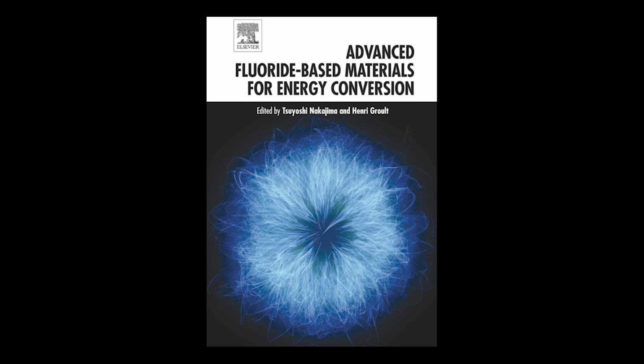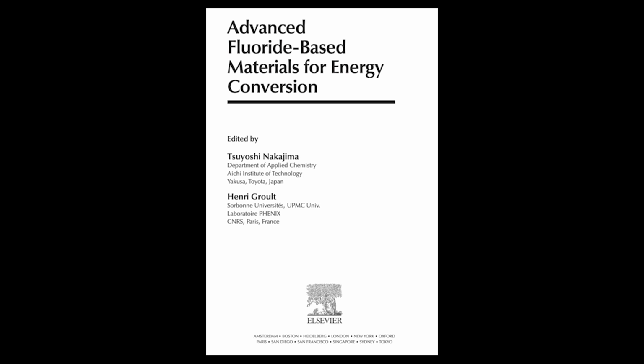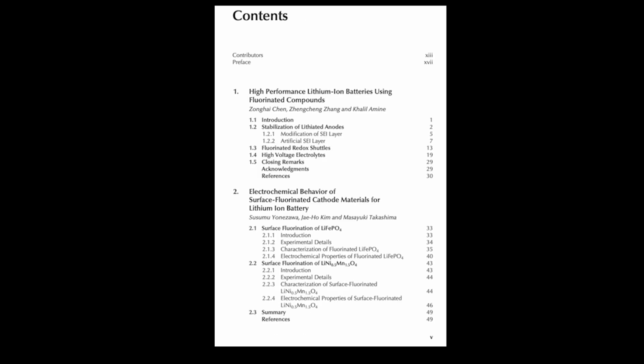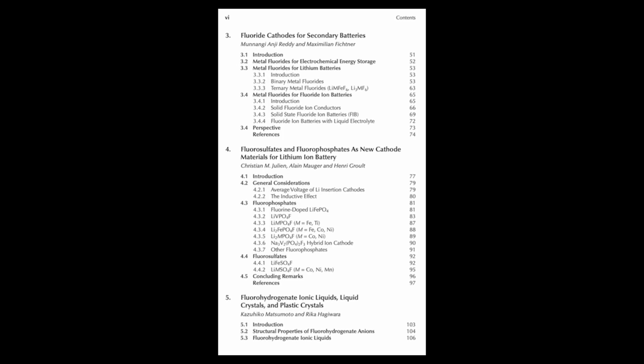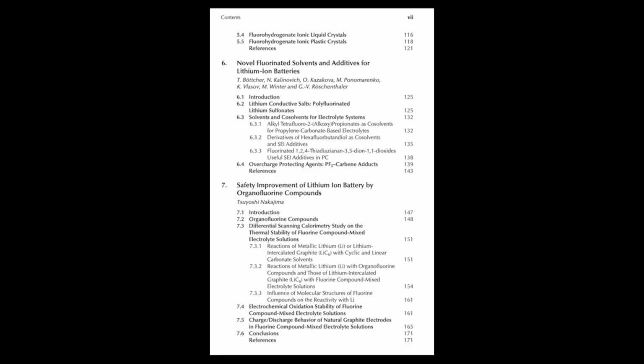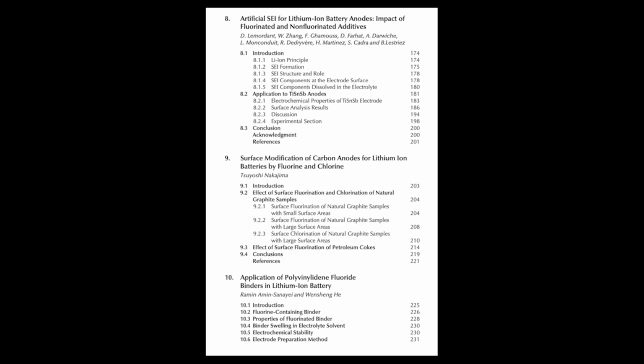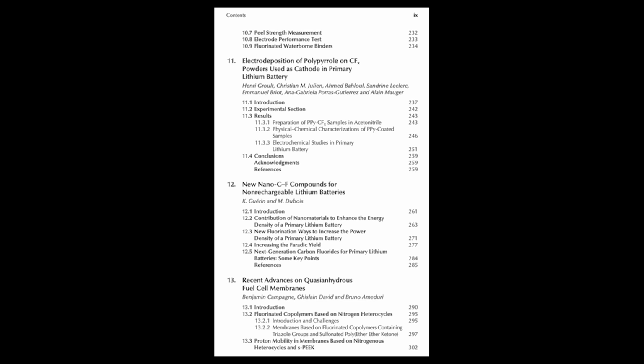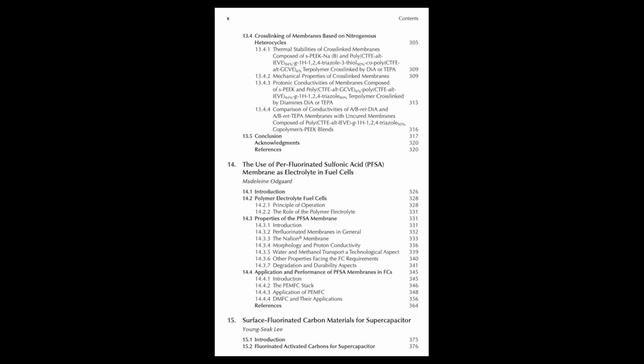And Nafion is well known for its ability to conduct protons, right? Hydrogen ions. Especially when it's wet. Exactly. When it's fully saturated with water, typically at lower temperatures like 80 degrees C or below, Nafion exhibits high proton conductivity, around 0.1 Siemens per centimeter, which is quite good. But less good when it dries out at high temps. That's the catch. Its performance can decrease significantly at higher temperatures, say above 100 C, as the water needed for proton transport evaporates. This is why there's a big drive towards high-temperature PEMFCs or HTPEMFCs, operating maybe 120 to 180 C. What are the advantages of running hotter?